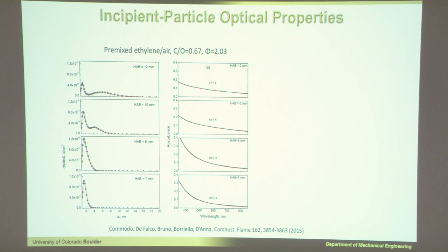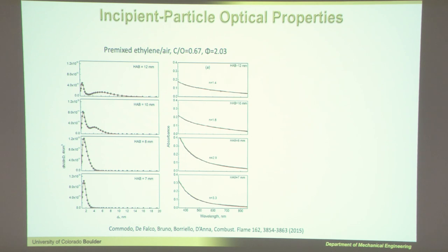As you go up in the flame, notice that the spectrum changes. Low in the flame, you're going to have stronger absorption at shorter wavelengths. And then as you go up in the flame, your spectrum gets broader as the soot matures. This is basically absorbance, or absorption cross-section. Notice that it gets flatter — that whole distribution gets flatter.